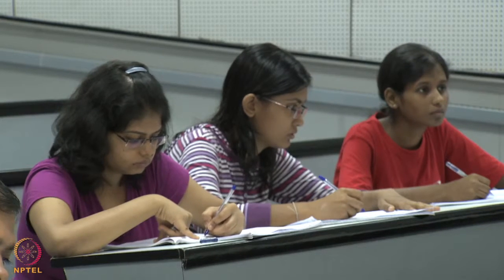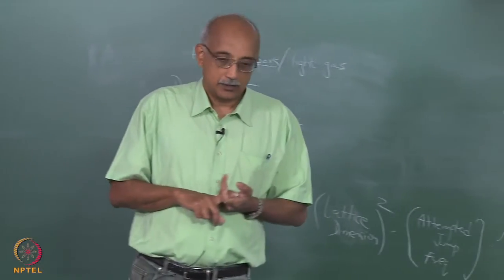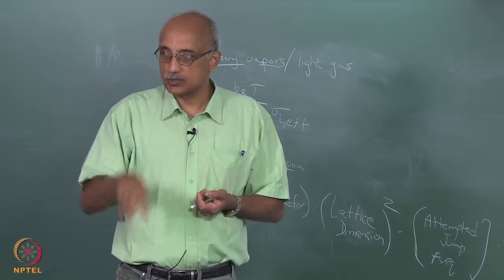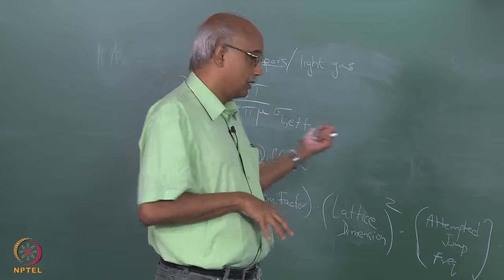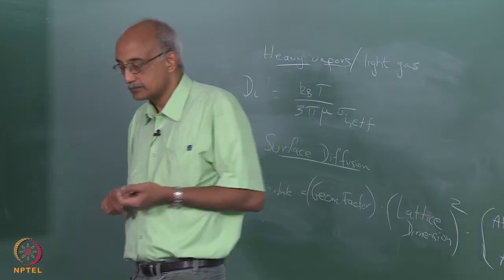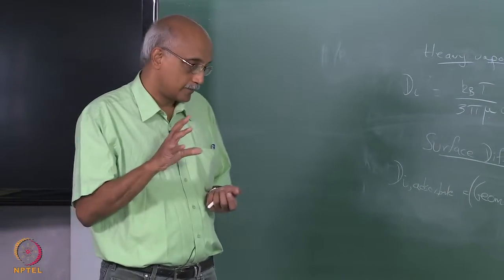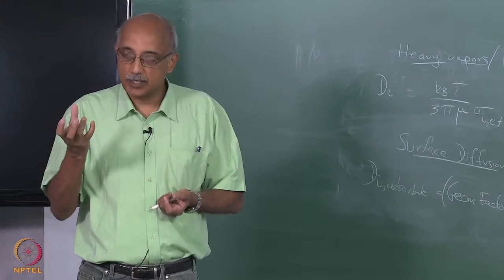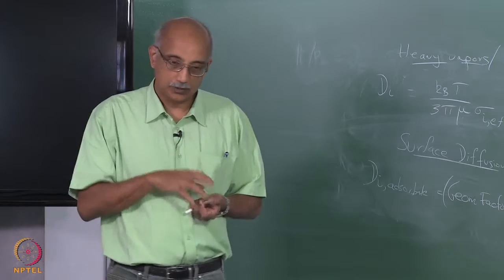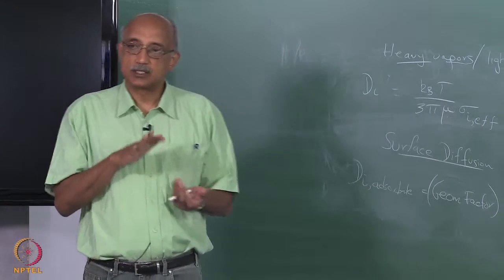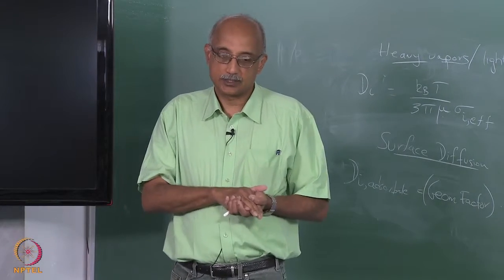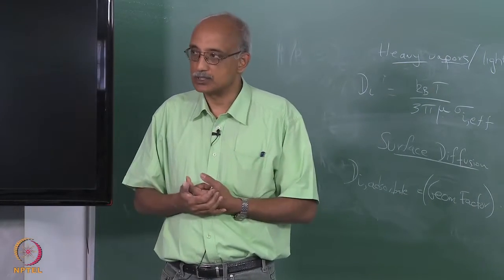So, the thing to remember with diffusivity is that there is no single expression for it. Depending on the particular physical situation at hand, whether we are talking about the diffusion of the precursor vapors to the substrate, that is governed by a different flux diffusivity coefficient, and then the actual migration of agglomerated or heavier atoms is governed by a different diffusion equation. And finally, once the diffusing molecule has been adsorbed on the surface, its diffusivity on the solid surface is governed by a different equation. And the effect of temperature and pressure are very different in each of these cases.